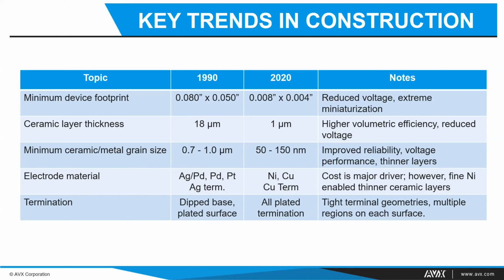I described the termination materials that are standard up here, but what is still a staple of the industry is really a dip termination. That's a cermet that's applied in a thick film fashion. However, in the past decade, there's been a rise of all plated terminations on devices, where electroless plating can be used to lay down base layers, followed by plated regions that match those. And this has allowed for some tight terminal geometries and multiple regions of termination across each surface of the device. So that, although not really ceramic related, has done as much for advancing the case of these types of devices as almost any development.